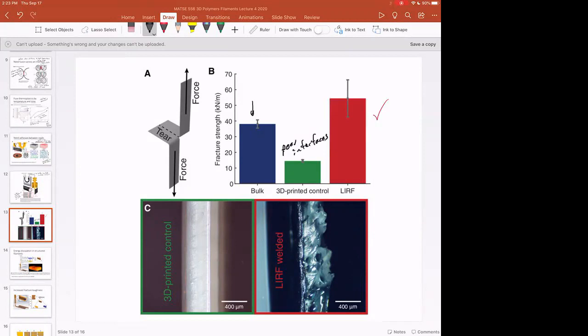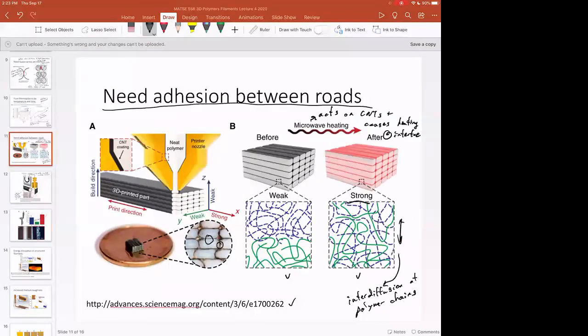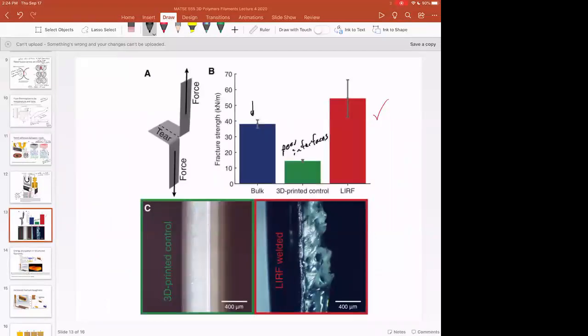And so with their microwave RF process, they're able to really increase the interfacial strength, and they're putting nanotubes in there, which might help increase the fracture toughness further. So this is an interesting paper because they talk about a technology, and then they talk about the fundamentals that that technology addresses in terms of what's happening with the polymer. And so it's a nice example of connecting some solution to the physical situation of chain interdiffusion, which is the connection that we want to make in this class.